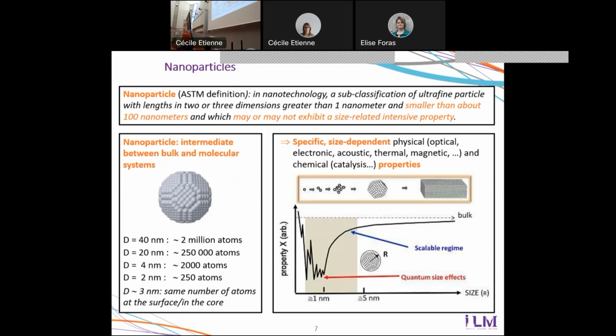I will explain. When you have sizes of a few nanometers, the particles will be made of a number of atoms, which is shown here. For instance, 40 nanometers corresponds to a few million atoms. But if you reduce to 4 nanometers, it's only a few thousand atoms constituting the nanoparticle. Also, an interesting threshold is 3 nanometers. That's when the number of atoms at the surface of the nanoparticle is approximately equal to the number of atoms in the core of the particle. With such sizes, a nanoparticle is actually an intermediate system between atoms and molecules, so few atoms, and bulk solids made of a very large number of atoms.